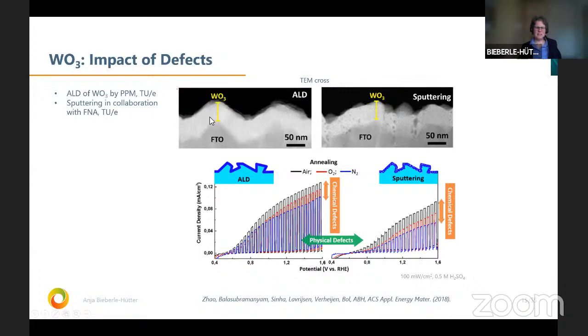here we have an ALD film of 50 nanometers. I mean, we just got this because we said we would like to compare the sputtering to the ALD, but this takes so long time. ALD is more for thinner films, yeah. So, but what we learn from this study, when we see that the performance is better for the sputtering, we need to tune the sputtering to get to better layers there, for example.